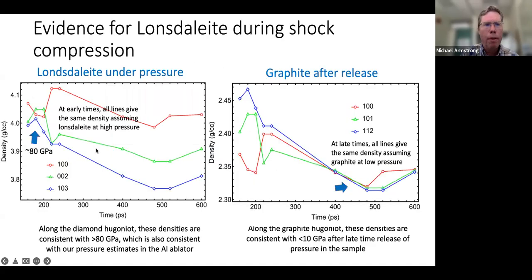Well, over these time scales, you might have noticed that the graphite in this only lasted for tens of picoseconds. It might be possible to use some coherent Raman technique, but usually the limitation, if you're using spontaneous, is you just don't get any photons out, right? So if you were to use some sort of three-wave mixing, multi-wave, four-wave mixing, you might be able to get enough out. But I do feel like